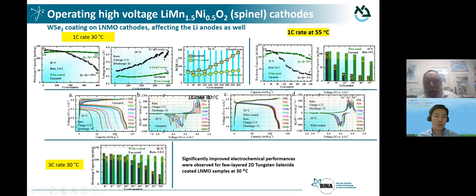So you see results at 30 degrees C and 55 degrees C. LNMO is known to be very problematic at elevated temperature. We could demonstrate stabilization. Look, compare the black reference and the green coated materials. We see stabilization, which is impressive. We stabilize the capacity. We also stabilize the voltage. We stabilize the resistance. You see some voltage profiles as well.